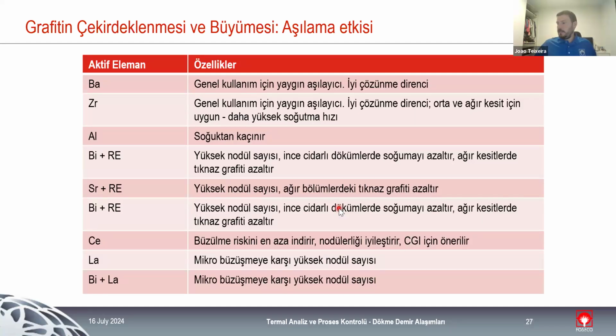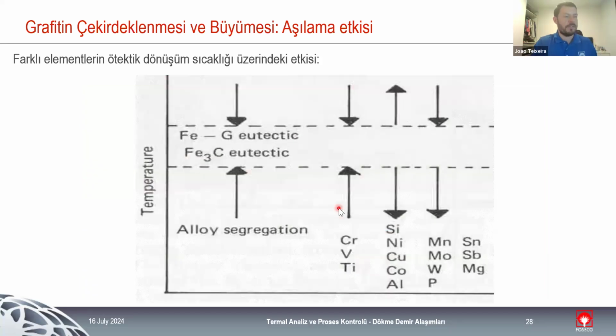And in here, we have the main active elements for inoculants. There are some other elements that are not present here, and there could be a lot of playing between one and the other, but basically it's barium, zirconium, they are the universal ones, aluminium. It's also used in 99% of the inoculants. Aluminium is really important because the crystal phase of aluminium is the same phase as for graphite, so it's easy for graphite to grow on top of aluminium crystal phase. Bismuth, rare earth, strontium are ones that are really used for gray, cerium, lanthanum, and then a combination of different active elements. We can play a lot with this, and again, we have dozens and dozens of different inoculants in the market.